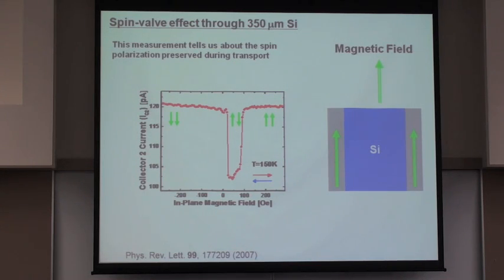Of course, continuing to increase the magnetic field on the other side will result in orienting both of the magnetizations with the magnetic field and recover a parallel spin signal. Of course, you see the same signal reflected about zero when you reverse the field sweep to reflect the ferromagnetic remnants in hysteresis. Okay, now these kind of measurements are very important because they allow you to make a measurement of the spin polarization of the electrons after they've traveled through the silicon. And so by varying the amount of transit time through manipulation of the internal electric field, we can then use that in a measurement of the spin lifetime.